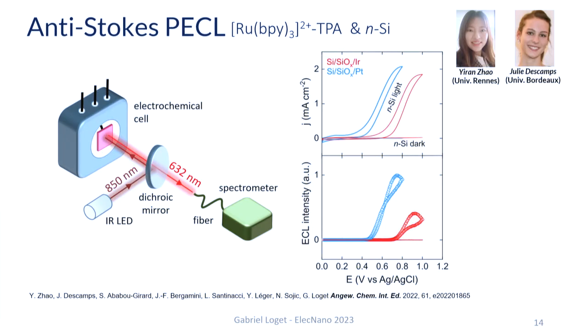So here you see on the top cyclic voltammograms obtained in the dark or under near IR illumination for two different metal protection layers. So in red, iridium, in blue, you see platinum. And in the bottom, this is the same potential x-axis. We see the luminescence intensity, which was recorded simultaneously.